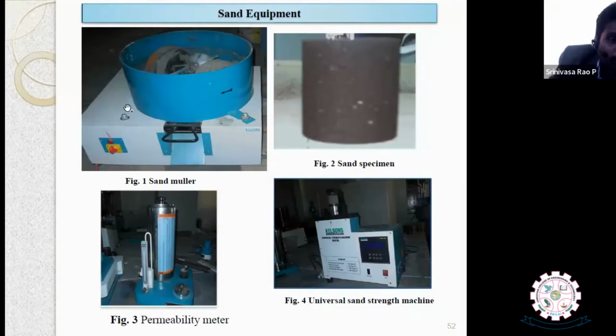So with variable proportions we have added materials, and we made the green sand with the help of a sand muller. After making the green sand, we made the sample out of the sand composition by using a sand rammer. With the help of the sand rammer, we make the sand sample, and this sample is used for testing, to test the permeability and the tensile strength of the sand.